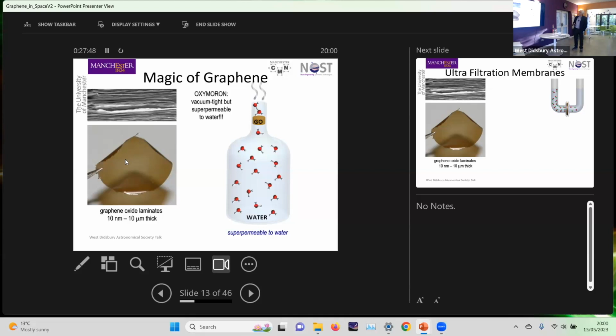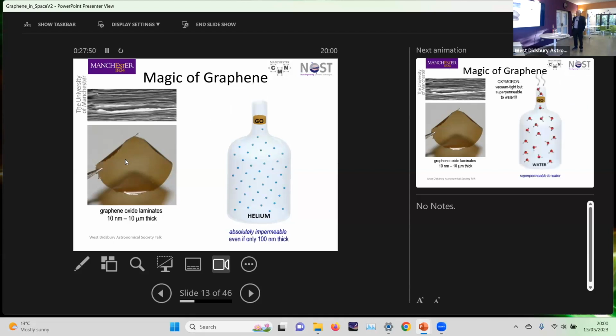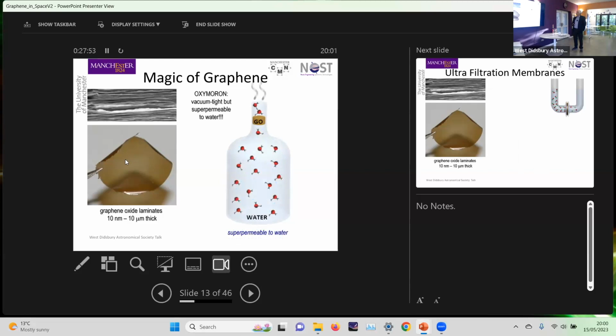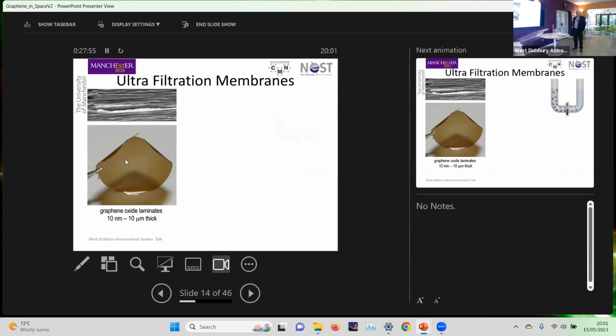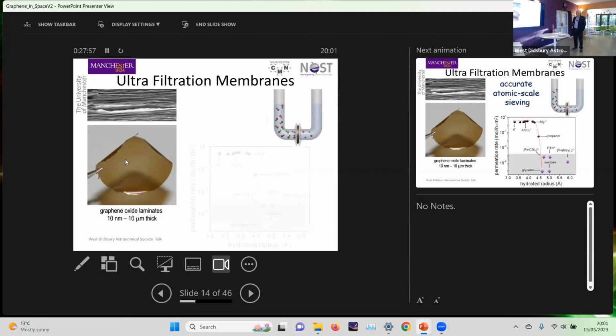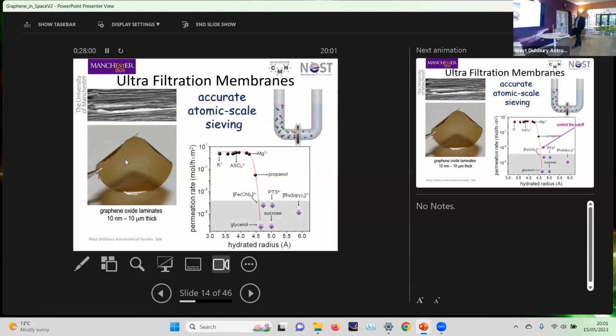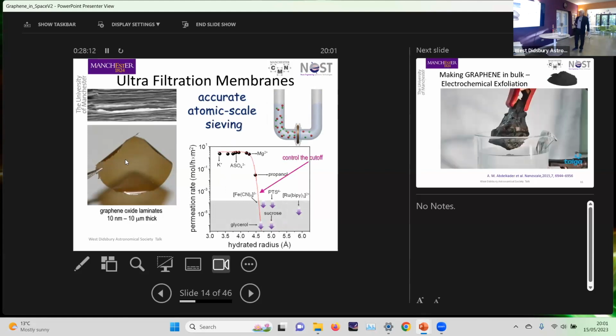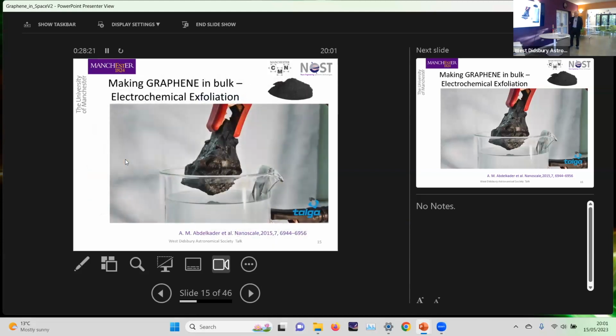So although it looks like a bit of an oxymoron there, it isn't. It works quite nicely. And of course, further work has been done to make filters out of this stuff. One of the things that we found is that you can filter out molecules of different sizes because you can make that cutoff between where the molecules will go through and where they won't. You can make that programmable, so you can move it up and down. So obviously, as a filter material, this looks quite interesting. I just mentioned that, we'll see that later on.